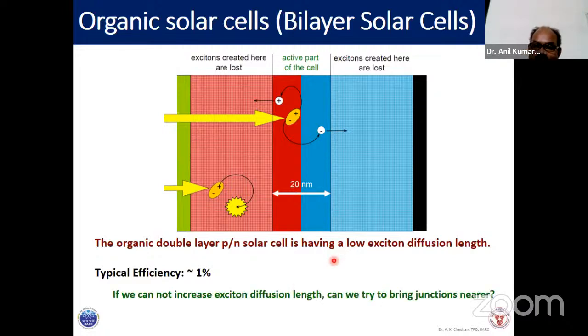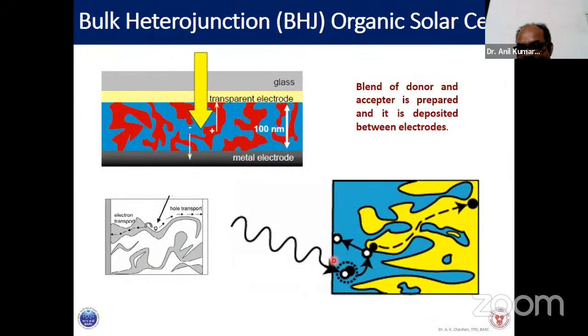So what should we actually do? The structure which works in silicon is not going to work in polymer solar cells. If we cannot take the exciton to the boundary, we can bring boundaries to the exciton. How can we do that? We make a blend, and that is called the bulk heterojunction. You make a blend of donor and acceptor materials and deposit it between two electrodes. Now if an electron hole pair is generated, it invariably will see a boundary very close to it. A boundary is necessary in order to dissociate an exciton.